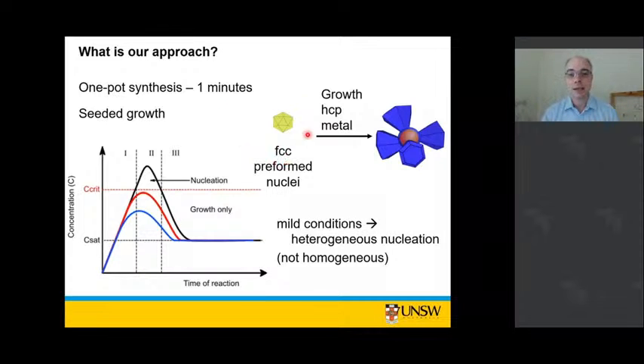So we often use gold nanoparticle seeds because gold always has a clean surface as well. It doesn't tend to oxidize. And then off that FCC structured seed, we want to grow a hexagonal close-packed structured metal to get our branches. So ruthenium is a hexagonal close-packed structure.